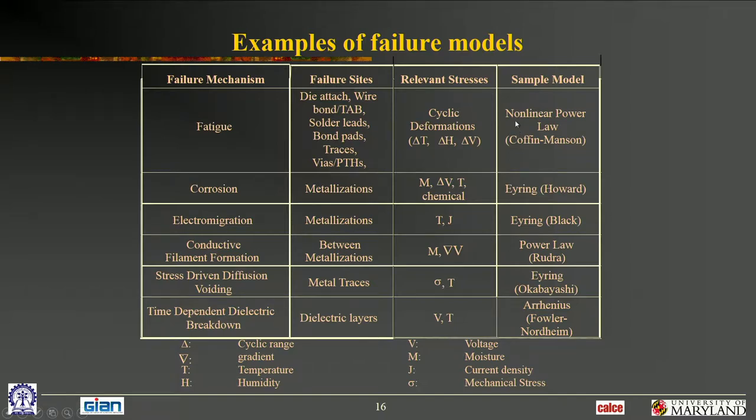There are high temperature metals being used everywhere in engine exhaust, combustion chambers, high temperature superalloys being used everywhere. So the fatigue community has long ago solved that problem of how we handle high temperature creep fatigue. All we've got to do is apply it to electronics. Because believe it or not, electronics are high temperature products because you're so close to the melt temperature of some of these materials. Electronics are operating in the same homologous temperature domain as high temperature superalloys in combustion chambers and exhausts. That's the domain of operation we have.